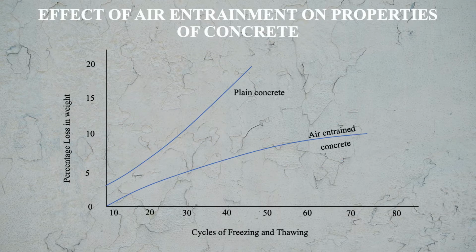So as the number of cycles of freezing and thawing increases, the percentage loss in weight is more for plain concrete in comparison to air entrained concrete. So this figure shows that there is an advantage of using air entrained concrete in the freezing and thawing process.